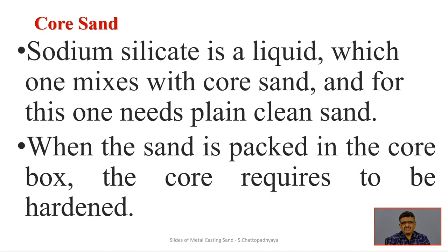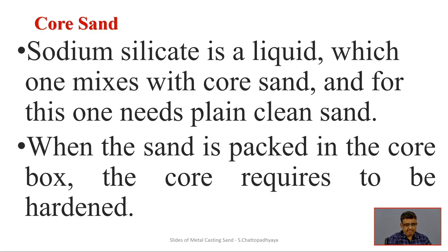Sodium silicate is a liquid additive mixed with clean sand to give the required property. When the sand is packed in the core box, the core requires hardening — hardenability is important because the core will be surrounded by a turbulent flow of molten metal that can jeopardize the geometry of hollow sections. The core can be hardened by leaving it exposed to carbon dioxide, which acts as a hardening agent. The degree of hardening depends on how much the core is exposed to the carbon dioxide environment.